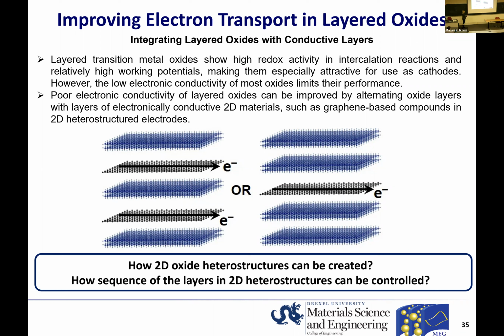Wouldn't it be nice if we synthesized a layered oxide material where now and then we would introduce a conductive layer, such as, for example, graphene or MXene, which are highly conductive materials? In this case, the electrons would go through this conductive layer, and ions would still have interlayer spacings available for intercalation. But how can such structures be synthesized?